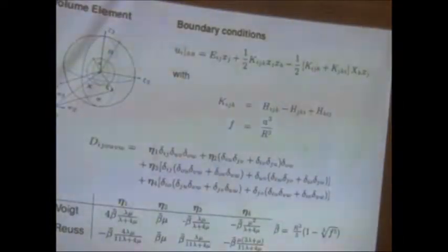Now this is the aim: not to have just a strain gradient elasticity to describe the problem phenomenologically, but to relate it to genuine properties of the material. Therefore, we opt here for such a homogenization procedure. This is the most simple case we can consider, but we can do better. For instance, we can do it in 3 dimensions, and here we didn't solve this problem analytically as before. We are prescribing the same kind of boundary conditions: a displacement field at the boundary which can be expressed by the mean strain and average strain gradients.